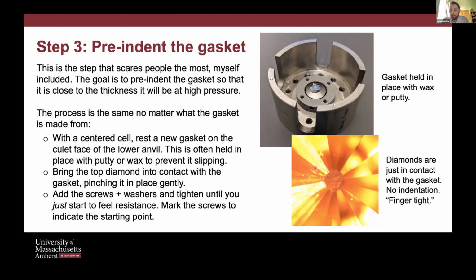What we're seeing here is we're looking through the back side of a diamond. So this is the inside of the diamond, if you will, and this is the culet. This circular-ish polished face is the culet, and it's touching rhenium. This grainy feature is the surface of the rhenium gasket, but it's just touching. And that's where we start from.